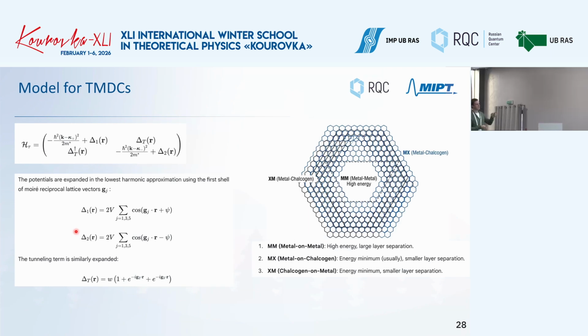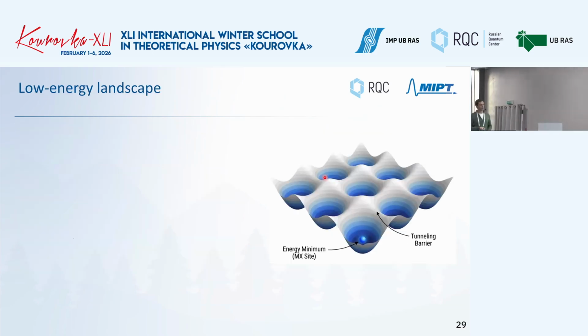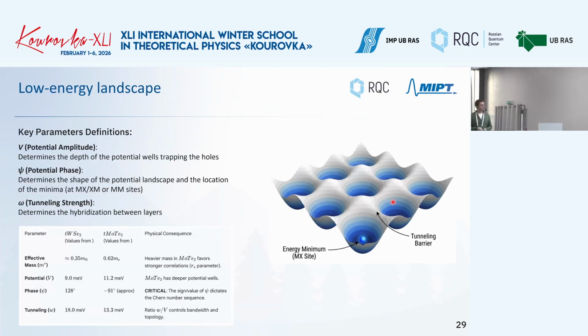There are tunneling parts, there are intralayer and interlayer terms, and also when you put one layer on top of the other, you see in this case you already have these metal ions and chalcogenides, and then there are some areas with lower energy potential and with larger energy potential. So you put one layer on top of another, then there are metal atoms and chalcogen atoms. When the metal is on top of metal, then there is high energy and large layer separation. The energy is minimum when the metal is on top of a chalcogen atom. So you form this sort of potential, a very deep potential compared to the graphene case. It looks like this. So you have a very deep potential and there is some sort of tunneling barrier between them. So for the carriers, it's difficult to hop from one side to another. And since the potential is much larger, then let's see how it goes.